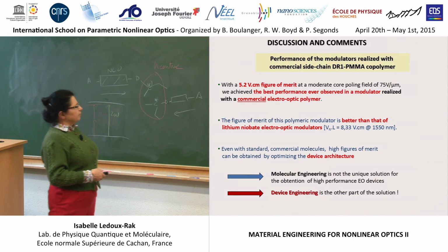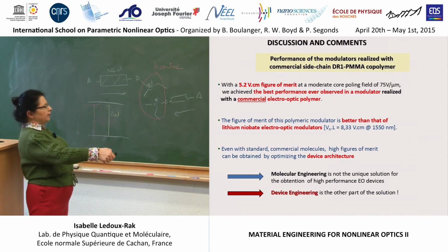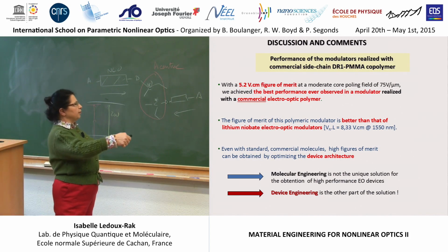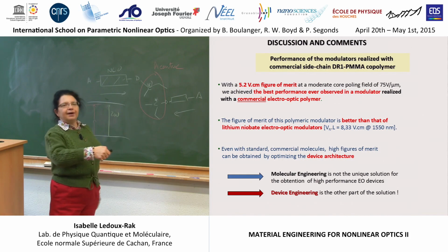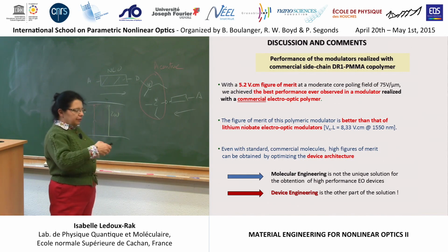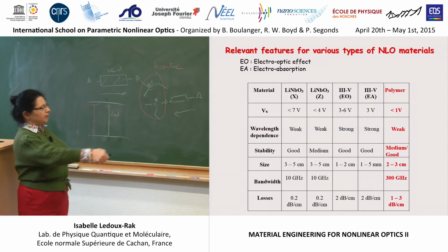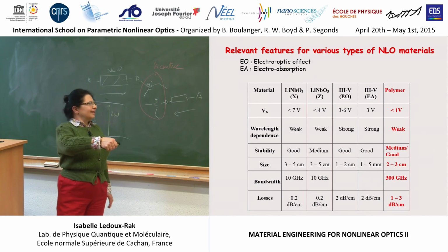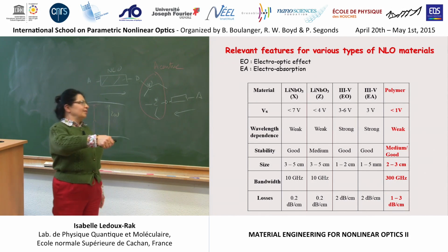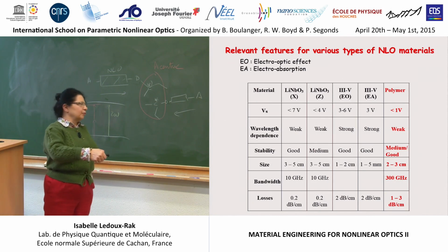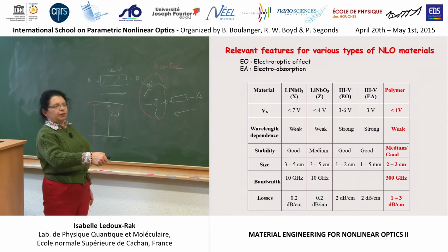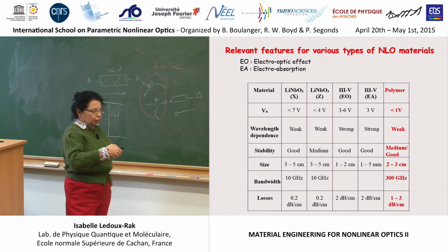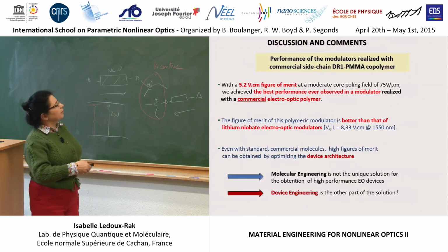So we have seen that it's possible to obtain a very good voltage and very good result, even with relatively low cost and commercial materials. Because the result I showed before, especially 1 volt operation, was found for these sophisticated molecules I showed this morning, with a system with low bond alternation properties, but these molecules are difficult to fabricate, they are not commercial, and they also have a small problem of not orientational but thermal stability.